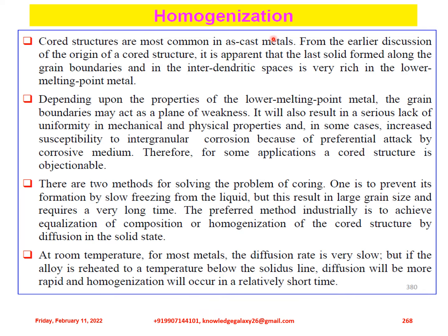Now let us discuss homogenization. Cored structures are most common in as-cast metals. From the earlier discussion of the origin of a cored structure, it is apparent that the last solid formed along the grain boundaries and in the interdendritic spaces is very rich in the lower melting point metal. Depending upon the properties of the lower melting point metal, the grain boundaries may act as a plane of weakness. It will also result in a serious lack of uniformity in mechanical and physical properties and, in some cases, increased susceptibility to intergranular corrosion because of preferential attack by corrosive medium. Therefore, for some applications, a cored structure is objectionable.